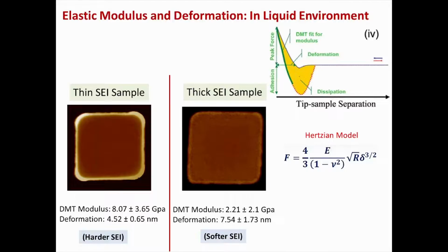One important thing in SEI is how you control the SEI to withstand these huge volume expansions and contractions. What you want is for the SEI layer to be a soft material so that it can stretch and come back, stretch and come back. It should not be stiff. So one thing that I tried was controlling the formation cycle in the very first cycle, so we can control the SEI thickness or how the SEI is forming. If I go through a very high voltage, like a 0.6 volt hold, it will be mostly organic, versus if I go to very low voltages directly, it will form mostly inorganic components.